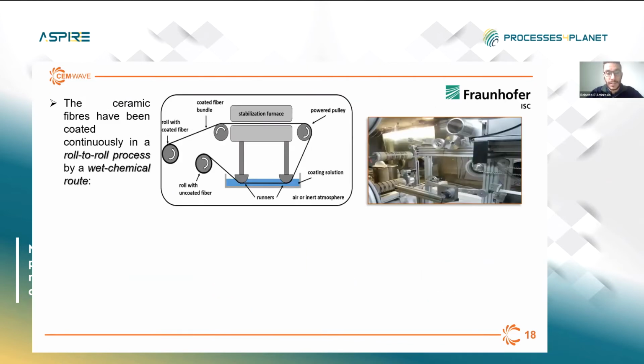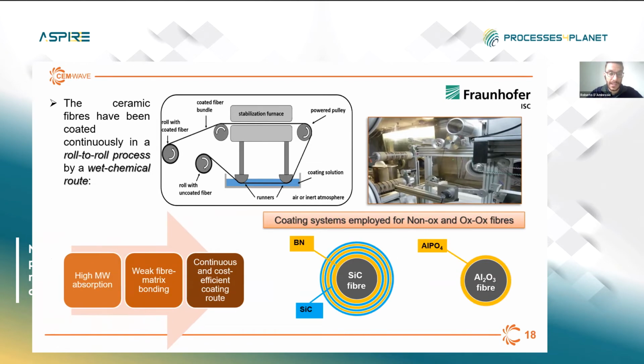The first step involved the interface coating of the ceramic fibers, which has been done in a roll-to-roll process by a wet chemical route, achieving in this way very uniform coating of the ceramic fibers in a short time span and continuously. The interface is a very crucial component for a CMC material, since by controlling the bonding strength between the fiber and the matrix through the interposition of this layer, it is possible to activate a series of toughening mechanisms under stress, resulting in its characteristic pseudoductile fracture behavior. And here I'm showing you the coating systems which have been employed for both categories of materials.